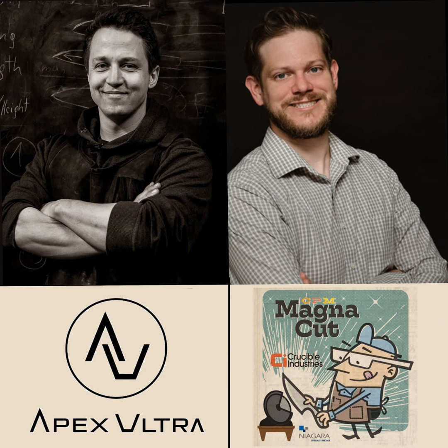can't go really far. It's a similar thing with heat treating. So if you have your steel austenitized, all the carbides are in solution, and then you quench it, there's no time for the carbon atoms to move in the solid state, to go anywhere. So they have to form martensite. But if you give them a lot of time, cool them down slowly, then they will go out of the matrix and form carbides instead. And if you give them a lot of time, there's going to be big carbides. You give them a little bit less time, the carbides are going to be smaller, and the steel is more homogeneous.